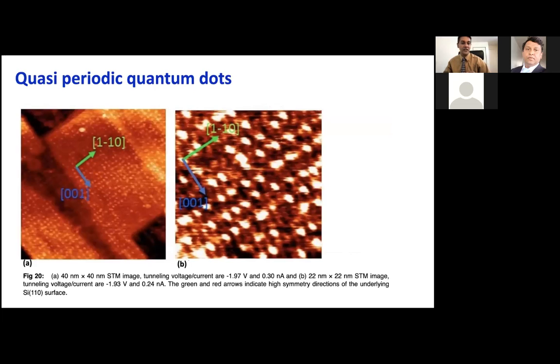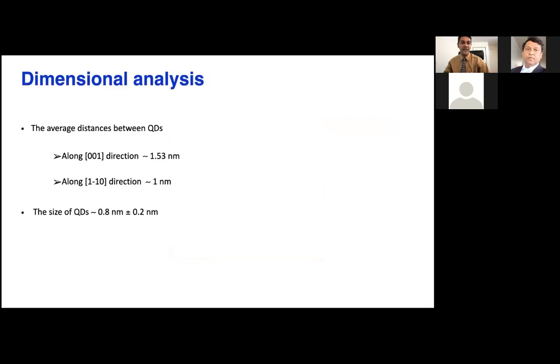You can see in figure 20, A and B, the high symmetry direction on the surface. This is quasi-periodic because it is periodic, but there's no order. That's why we call them quasi-periodic quantum dots. Before we do anything like nanowires, we analyzed the dimensions along the high symmetry 001 direction. The distance between the quantum dots is around 1.5 nanometers and around 1 nanometer. Am I running out of time? Yes. And the size of the quantum dots was around 0.8 nanometers.